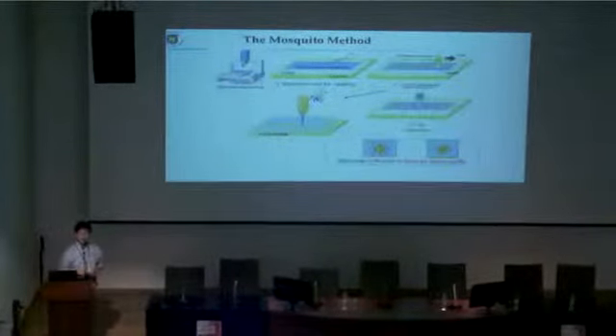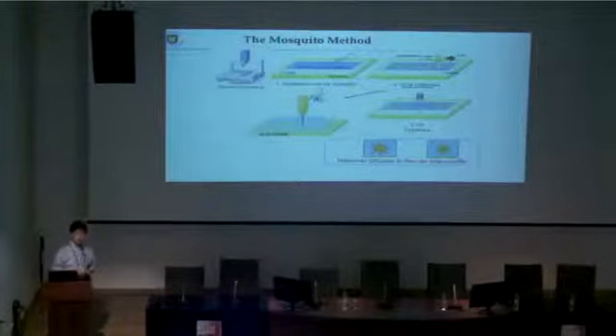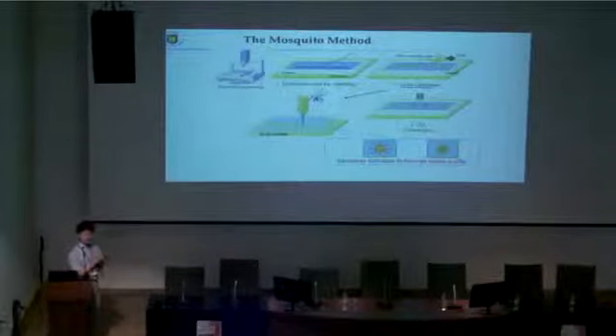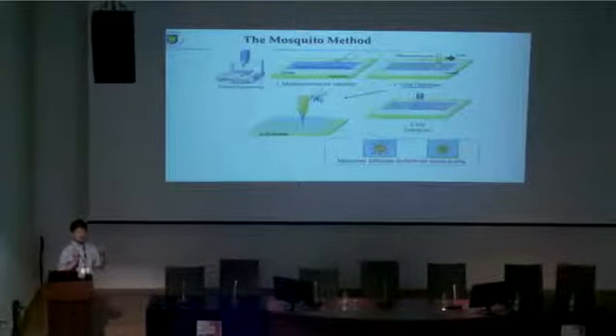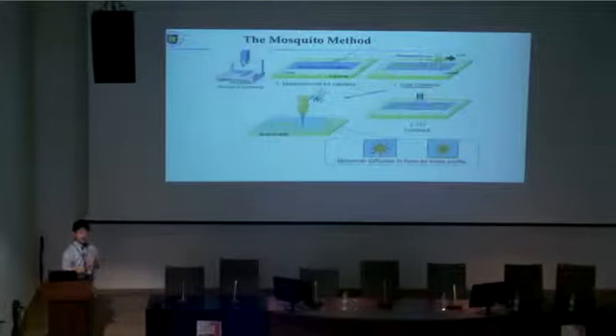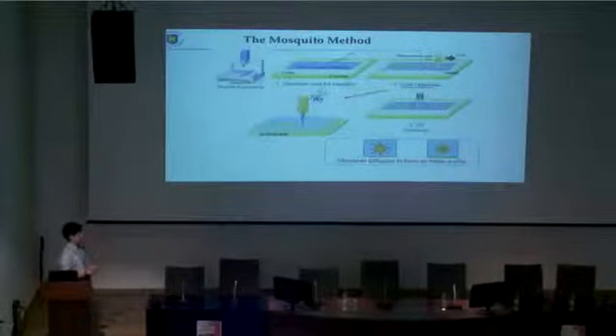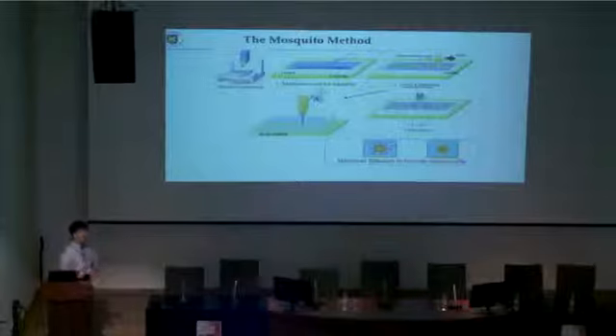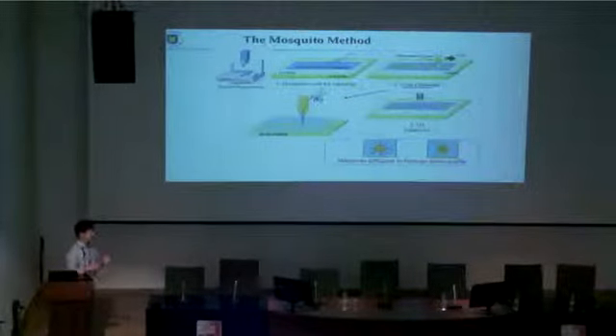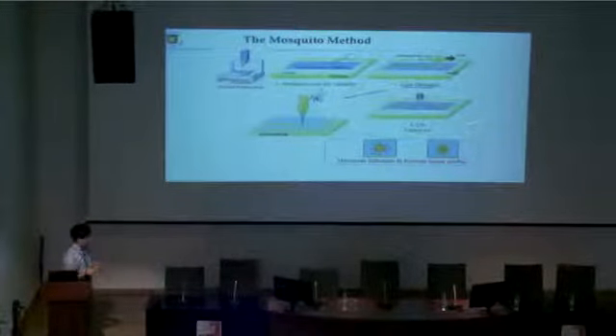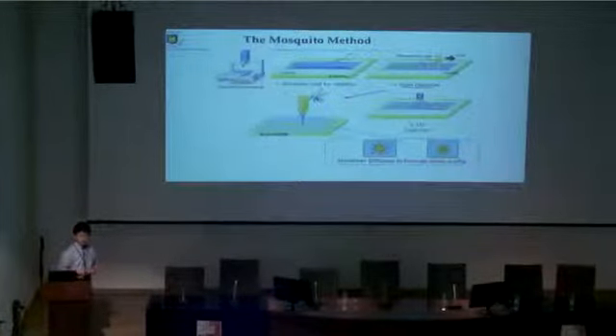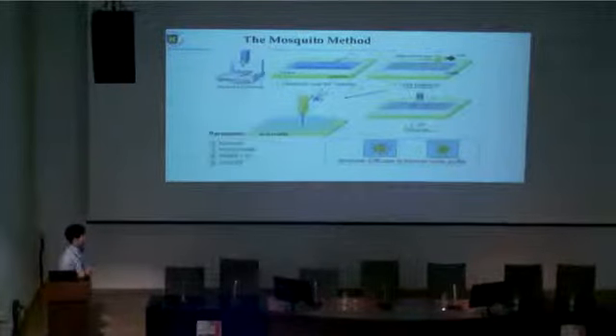And why is the refractive index profile obtained? Because you can imagine that toothpaste is squeezed into water. Then water is coming into the toothpaste, diffusion. The same thing is happening in this cladding material. The liquid cladding monomer can diffuse into the core to make the concentration distribution. Because the core monomer has a higher refractive index, the concentration distribution is leading to the parabolic refractive index distribution.